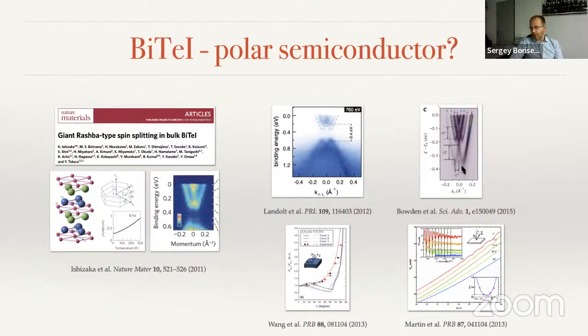And here is the beautiful data from Phil King's group showing that actually both sets of states are present, and in a very broad energy region. They interpreted this as quantum well states. So we realized that the situation in the ARPES community is not that unanimous. There is not a single opinion about that material.